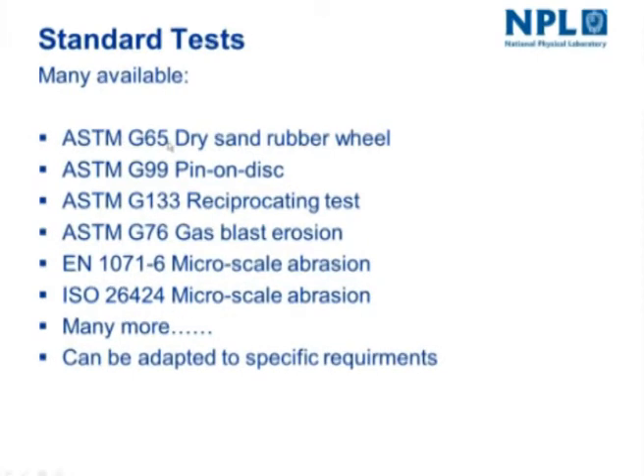ASTM G2 committee is a committee that's devoted to wear testing, so that should be a first source to go to. But CEN committees and ISO committees also are producing standards relevant to tribological testing. There are many more than the ones listed here, and it's important to note that these probably don't suit your particular application, but you should use these, if you can, as a basis for your specific requirements.